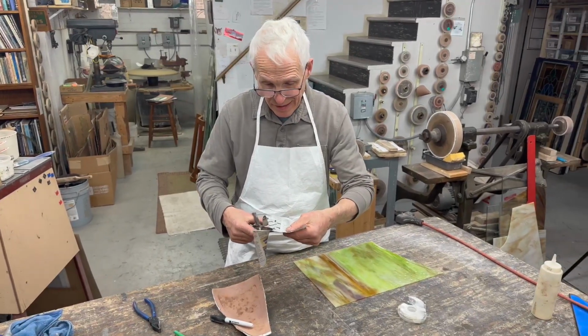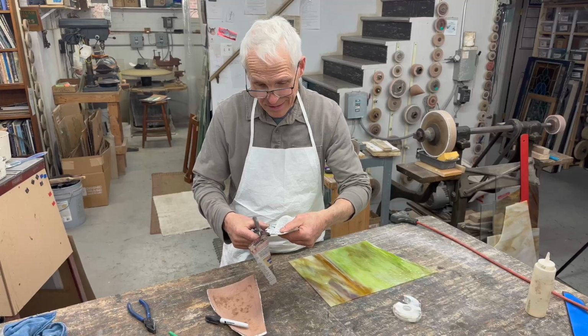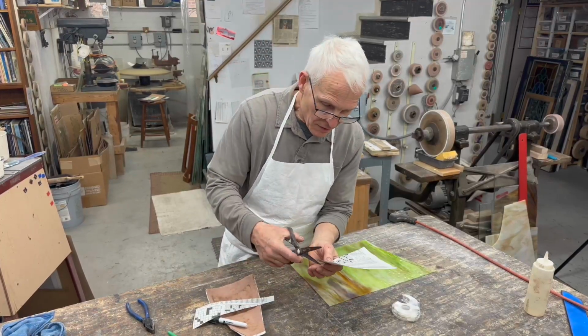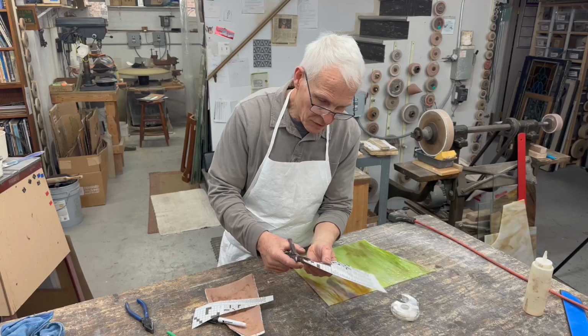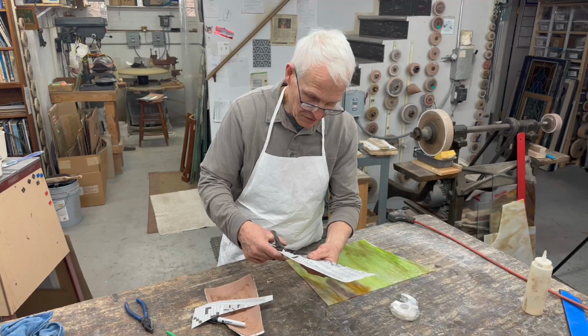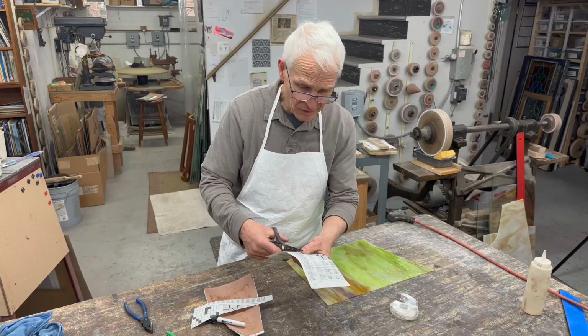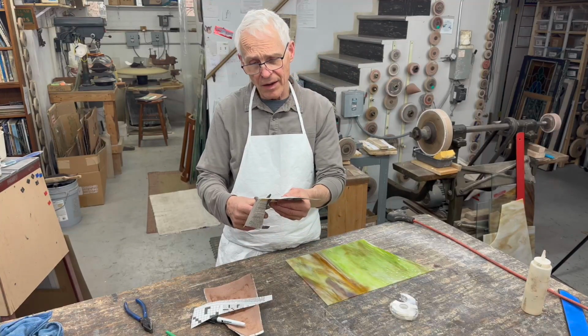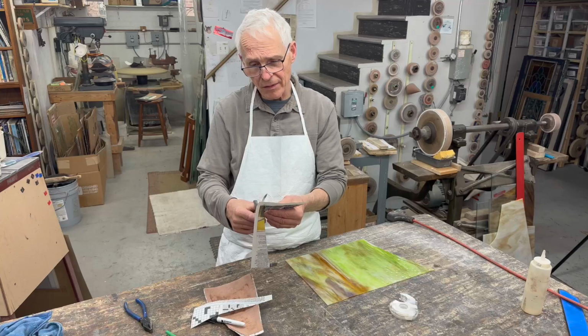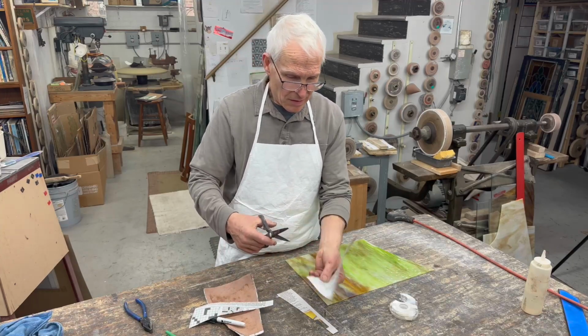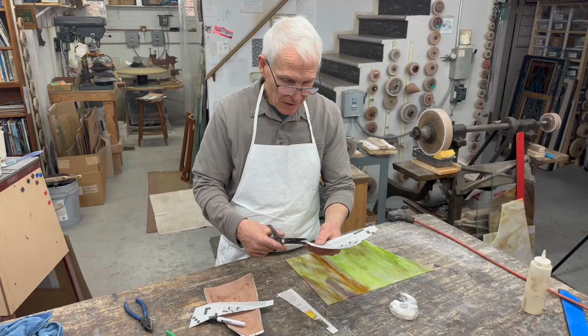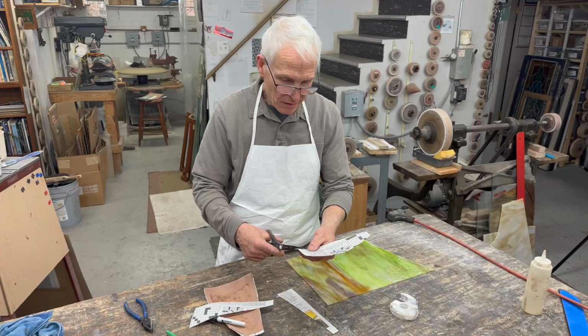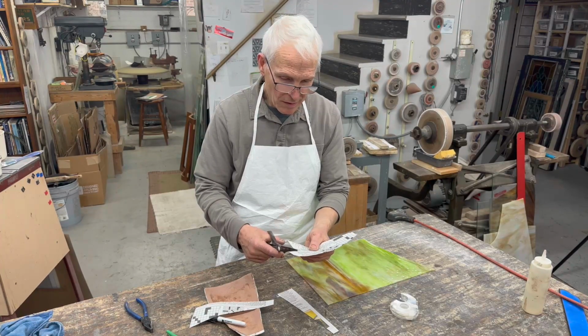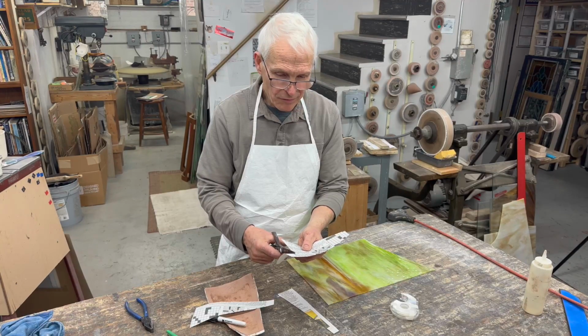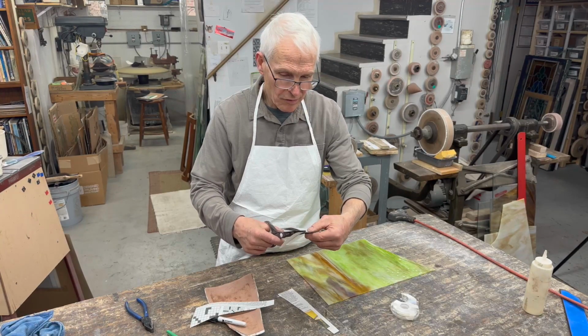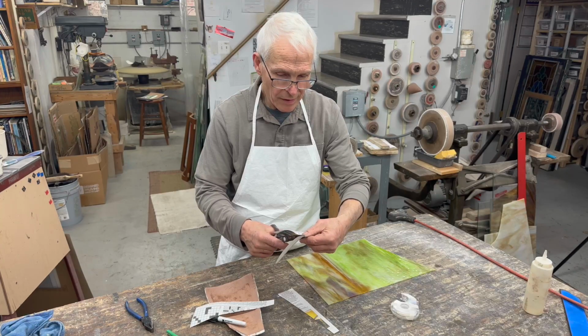Since it's opalescent glass, which is milky glass, we have to cut the pattern out. If it was just clear window glass, you could just lay the pattern down on the glass, on the table rather, and cut the clear glass to the line. Once again, we're going to cut it about 1/8 of an inch short to compensate for the fact that the paper pattern was draped over the front of the glass.